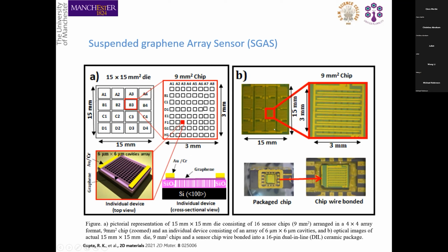This is just optical images of a chip with the 15 millimeter square as a starting die, and then you have one microchip, which is around 3 millimeter square. And on this 3 millimeter square, there are a lot of devices. So you get like 180 to 200 devices on it, which can be connected serially, or can also be connected in parallel in order to give you an averaging at the device level as well as at the chip level.